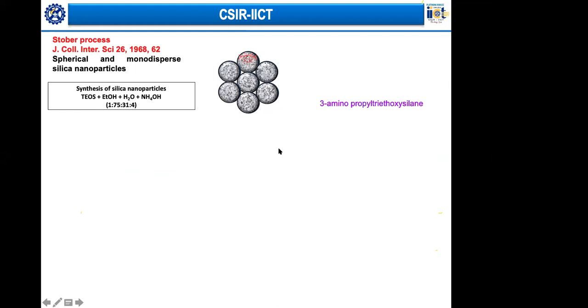Now, when we want to have the shell material on this, generally there is no friendly relationship between the two, because there is no bonding. That is why, when you have that kind of material for catalytic applications, leaching of the shell material is very easy, and it takes place in the first reaction cycle only. So in order to have these particles nicely bonded to the surface, we have to make some change. That is because these silica nanoparticles have OH terminals on the surface, so there is no way these metal nanoparticles can form bonds onto this.